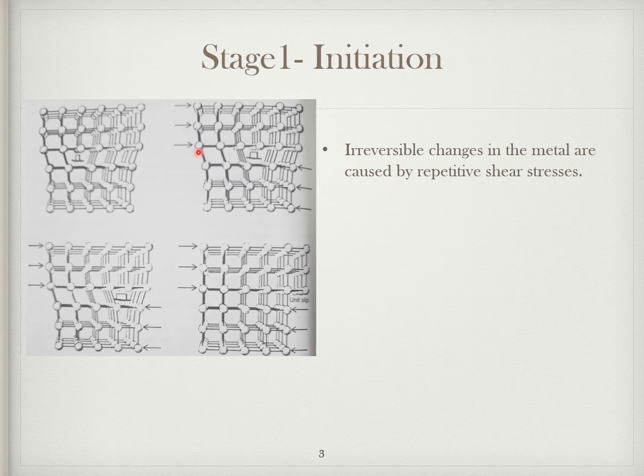So in this figure, we see that the stress is applied from the left hand side. So the edge dislocation which was present over here moves or jumps one unit cell to the right, and with subsequent application of the stresses, it further jumps to the right. And finally, to the edge of the crystalline structure. So here in the last figure, we see it has reached the edge of the crystalline structure. When the action is going on in many other crystals, the dislocations eventually join to form microscopic cracks. This is stage 1 in the fatigue process.